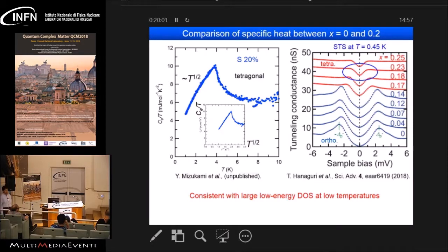Now we can also take a look at the tunneling spectra. So this is measured by STM again, and here the blue curves are in the nematic phase, in the low concentration side, and the red curves are for the tetragonal side. Okay. First of all, in the nematic phase or orthorhombic phase, we see a clear coherence peak, quasi-particle peaks. However, if you go to the tetragonal side, everything seems to be smeared, and we have a much smaller gap.